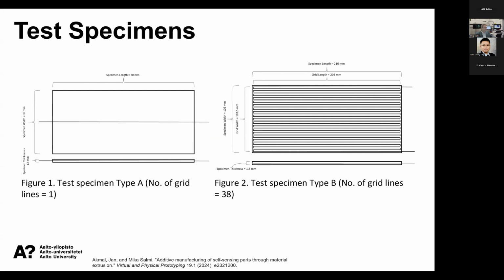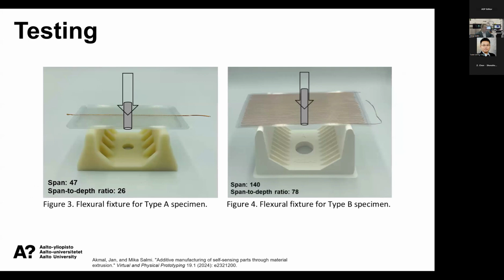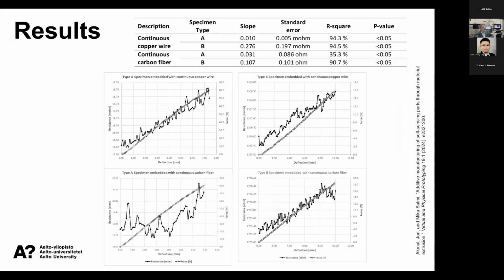We try to make the phenomenon stronger, so the resistance change would be bigger because there are more lines there. This is how we test it. We made a jig where we push the specimen, and we measure how much we are pushing and the resistance change, and these are the results. Actually, you can quite well predict how much it's been bent if you have enough fibers there. If we first look at this picture from the bottom left.